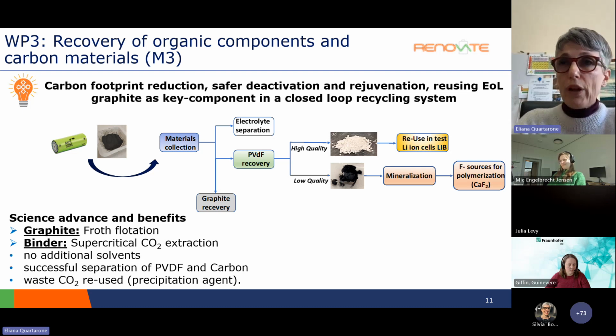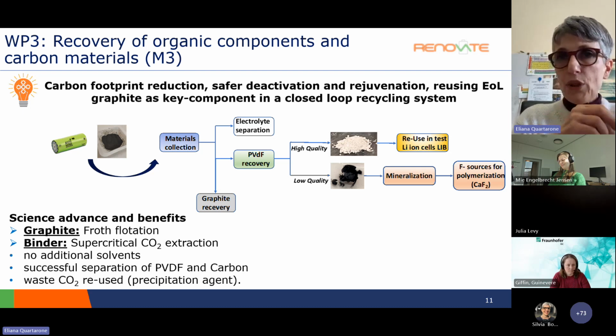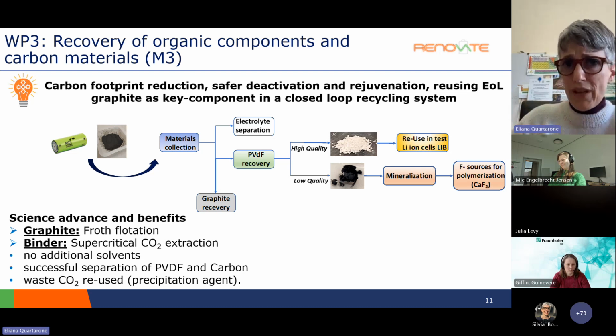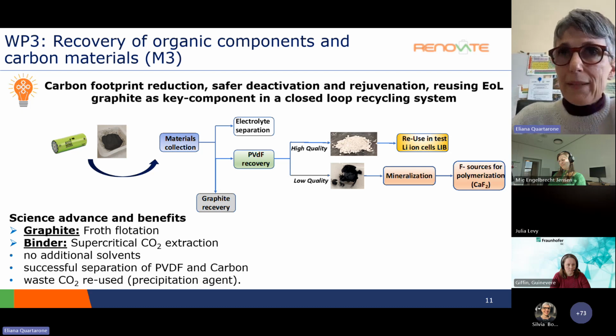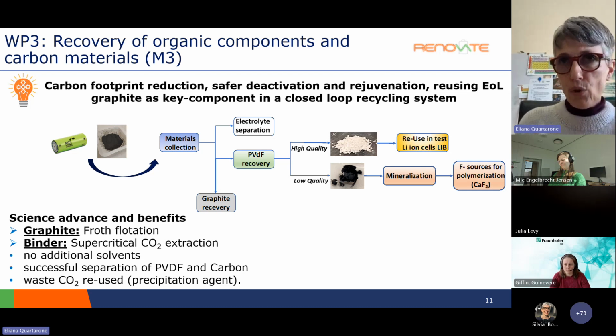Then we are also going to recover the electrolyte because, again, there is some value there, but also because the carbonates composing the electrolyte are flammable, as we know, and the removal of the electrolyte can make safer the deactivation and the recycling of the battery during the following steps. And finally, graphite, because recovering graphite can, of course, reduce the potential carbon footprint, but also graphite is a key component in a closed loop recycling system, so it can contribute to higher revenue, even if graphite is not yet considered in the battery regulation.